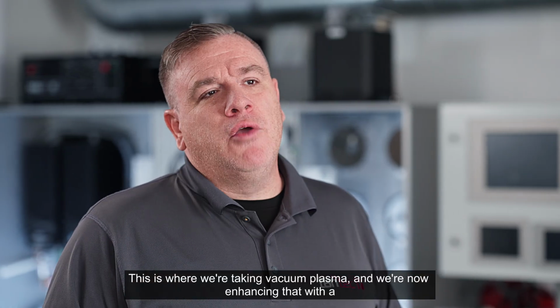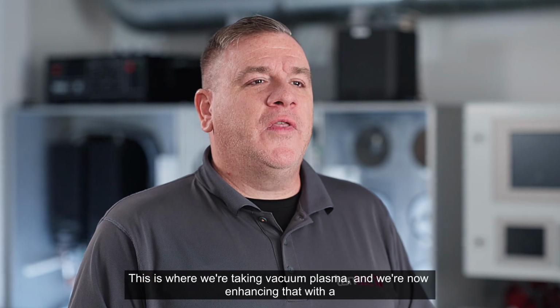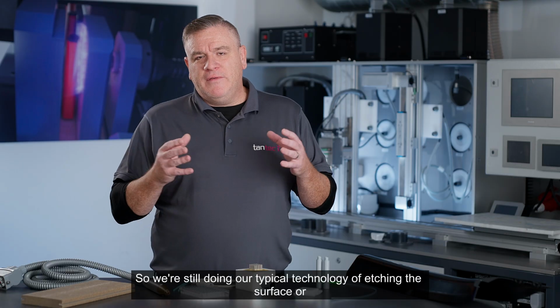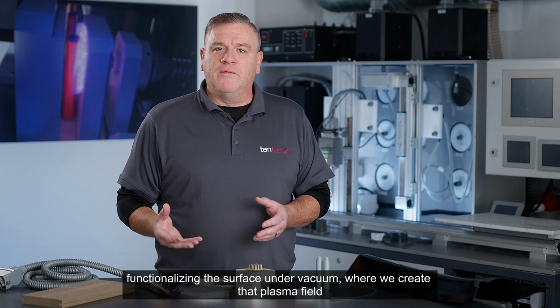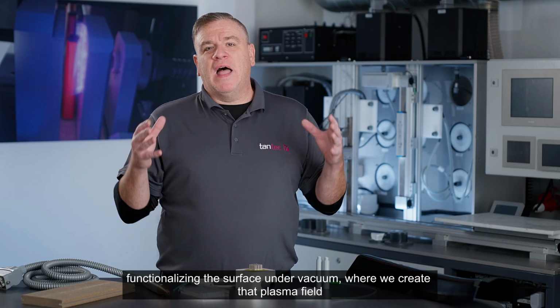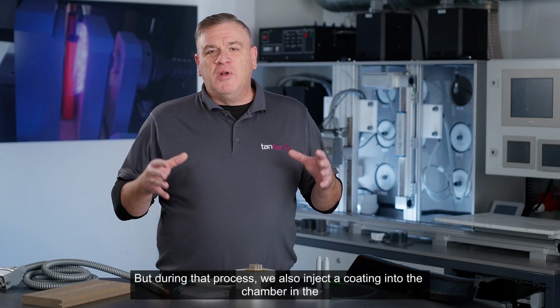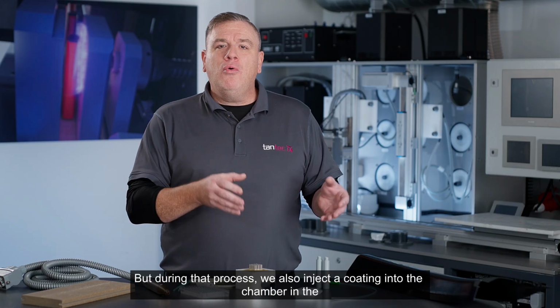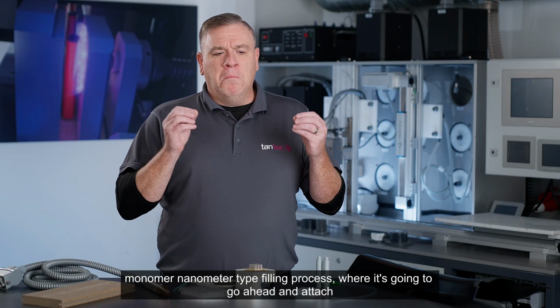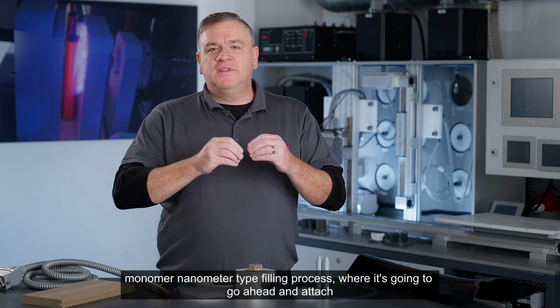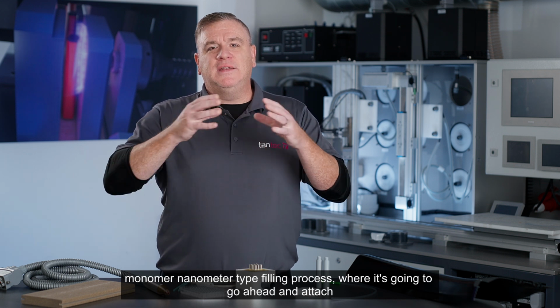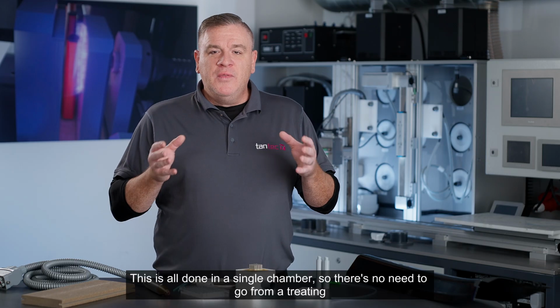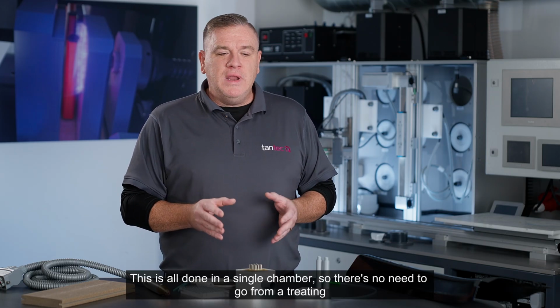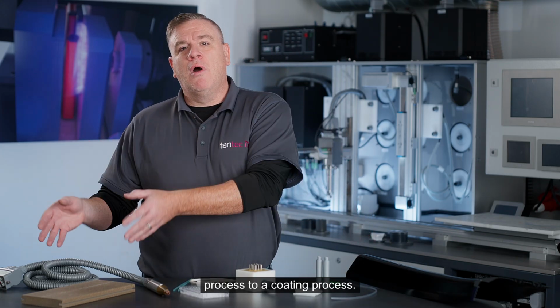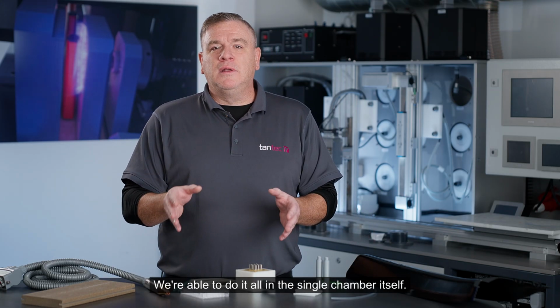This is where we're taking vacuum plasma and we're now enhancing that with a coating directly inside the chamber. So we're still doing our typical technology of etching the surface or functionalizing the surface under vacuum, where we create that plasma field while the parts are being treated. But during that process, we also inject a coating into the chamber in the monomer nanometer type filling process, where it's going to go ahead and attach itself to the surface of the parts. This is all done in a single chamber, so there's no need to go from a treating process to a coating process. We're able to do it all in the single chamber itself.